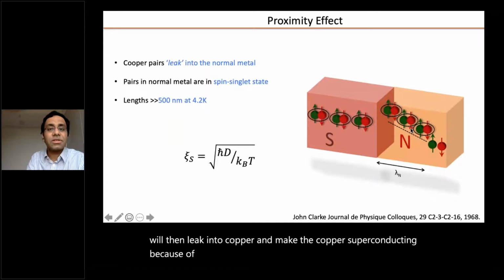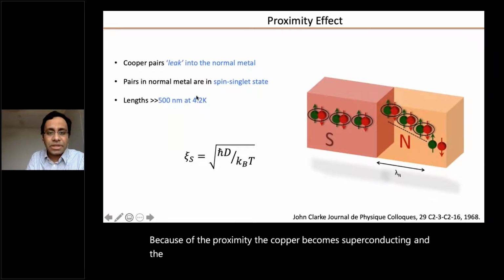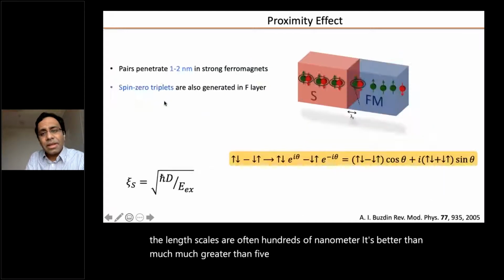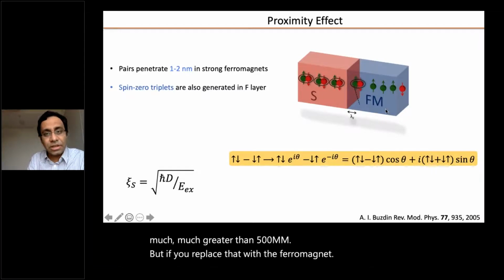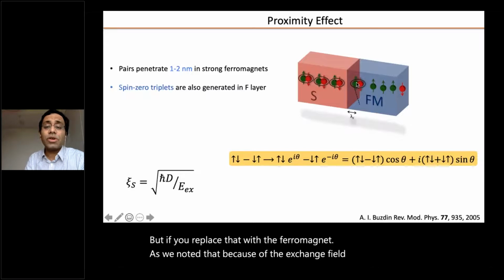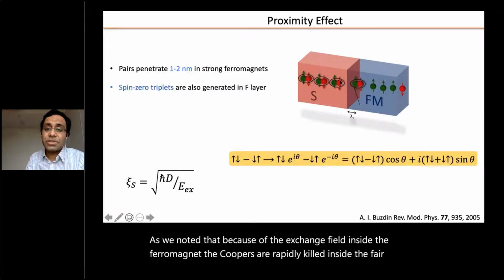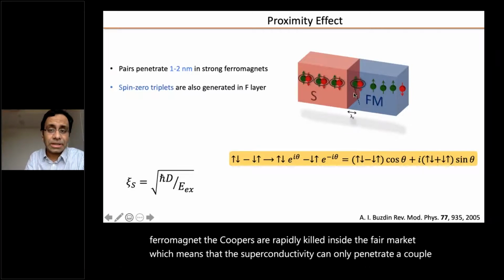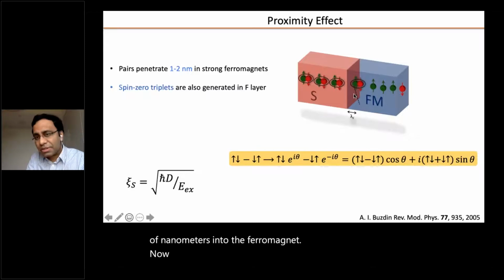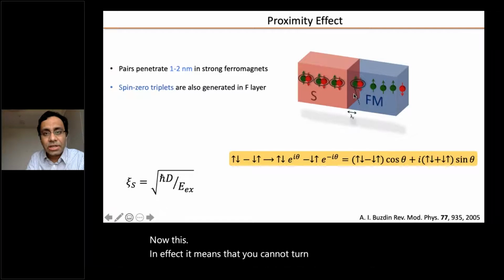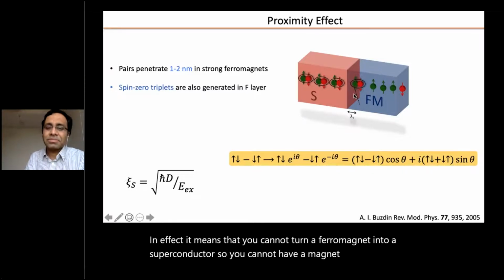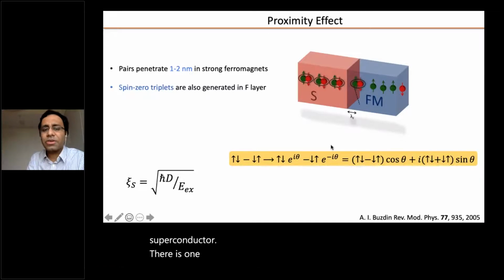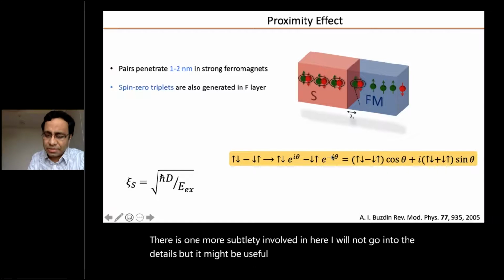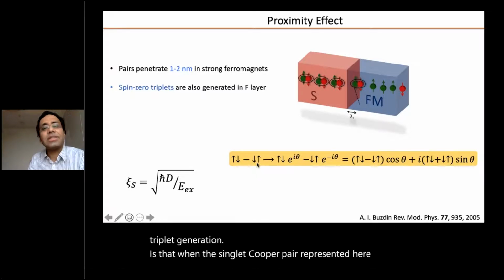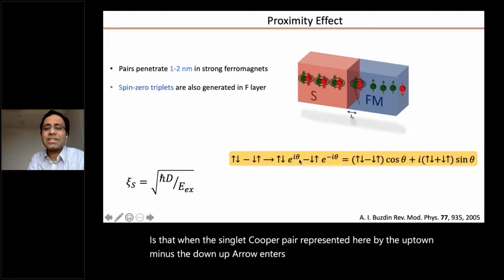Because of the proximity, the copper becomes superconducting. And the length scales are often hundreds of nanometers, much greater than 500 nanometers. But if we replace that with a ferromagnet, because of the exchange field inside the ferromagnet, the Cooper pairs are rapidly killed, which means that the superconductivity can only penetrate a couple of nanometers into the ferromagnet. In effect, this means that you cannot turn a ferromagnet into a superconductor. You cannot have a magnet which is a superconductor. And there is one more subtlety involved here. I'll not go into the details, but it might be useful to understand the next phase of the triplet generation: when the singlet Cooper pair, represented here by the up-down minus the down-up arrow, enters the ferromagnet, it picks up a phase.